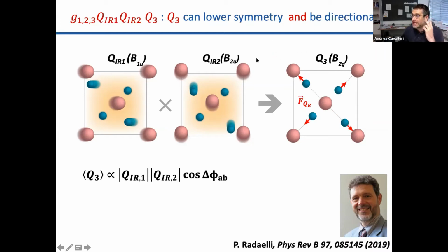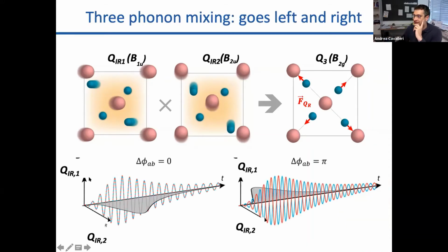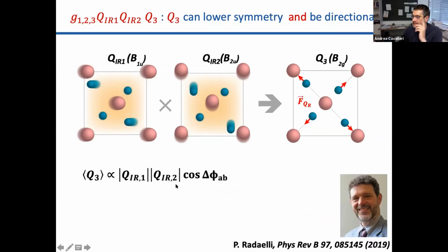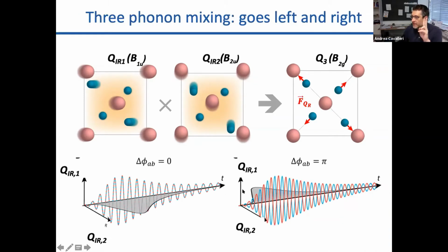And most importantly, the strength with which you couple to this mode will depend on the relative phase between this phonon and this phonon. So all of a sudden, you find yourself in a situation in which the force that you apply on this other mode is directional, meaning that you can either move it to the right or to the left, depending on the relative phase, whether this one is moving to the right and the other one is moving. So let's see. Depending on the relative phase between the two, if the phase is 0 or pi, the third mode will be displaced to the right and to the left.